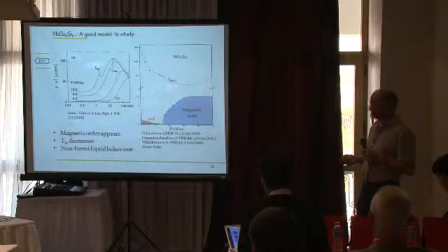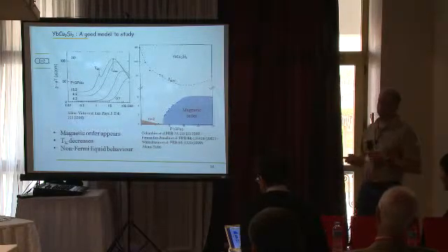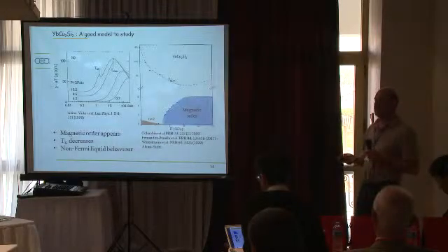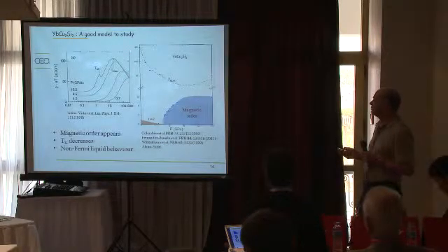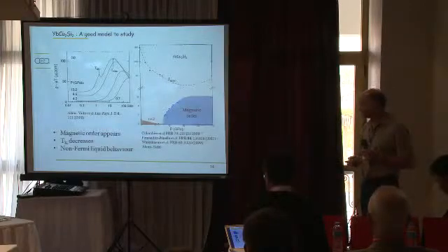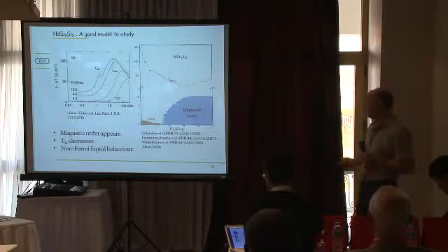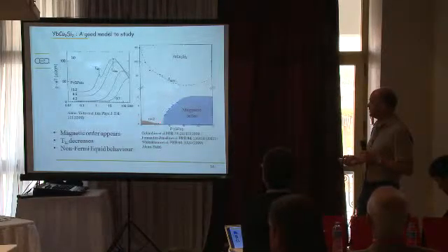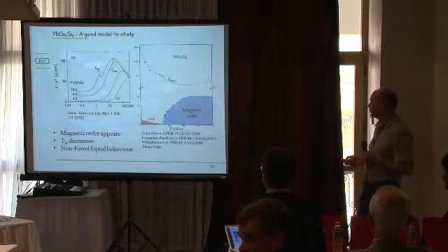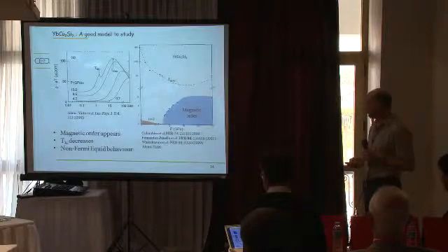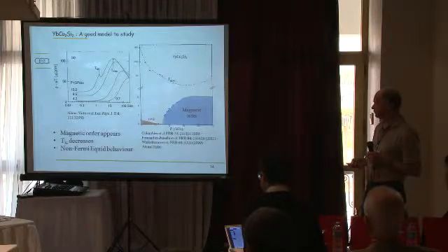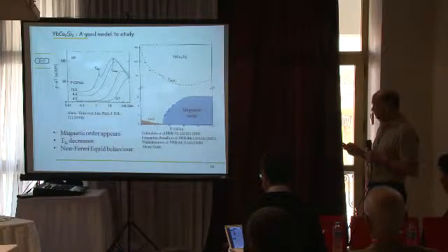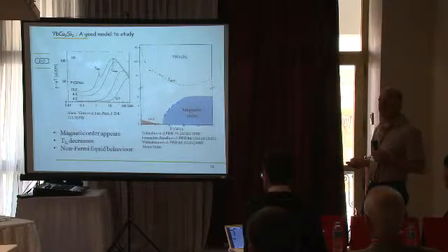I say it behaves as we expect because you see that in the resistivity there is also a maximum, and this is some indication of what the Kondo temperature is doing. The temperature where this maximum appears decreases with pressure, so we can think that the Kondo temperature is decreasing. If you look at the resistivity, you find Fermi-liquid behavior at very low temperature, and the temperature where Fermi-liquid behavior is present goes towards zero at the critical pressure. And in this region here, we get non-Fermi-liquid behavior with exponents which are smaller than 2. So basically, it's at least qualitatively obeying what we expect for quantum critical points from spin fluctuation theory.